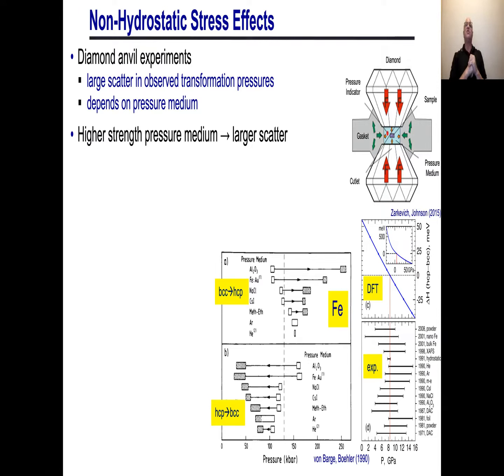Okay, so the point is, as you go to higher and higher strength pressure media, you're getting larger and larger scatter. The yield stress of helium is very low, basically zero, and so you have a very small range of measured values. On the other hand, as you go to a material that has a very high yield stress, the range of pressures that you see gets very large. And so people have for a long time attributed the scatter to non-hydrostatic stresses, and we'll talk more about that.